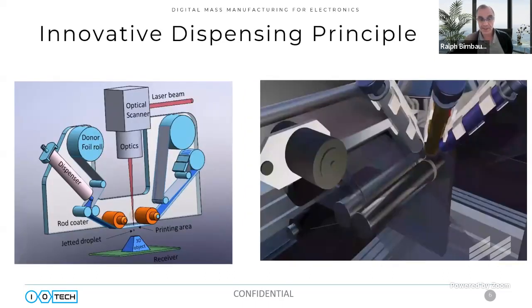The way it works is, on the left here, you can see a dispenser, which dispenses a material onto a thin transparent foil, which then carries the material through two rollers to guarantee a uniform thickness. It goes underneath the laser. The laser delivers a brief, powerful pulse of energy, which creates a vapor bubble, pushing a drop of the material onto the substrate below. And it can then do that over 2,000 times every second. Any unused material is then carried back to be recoated and reused a number of times.